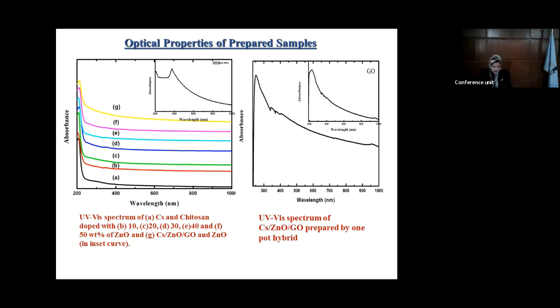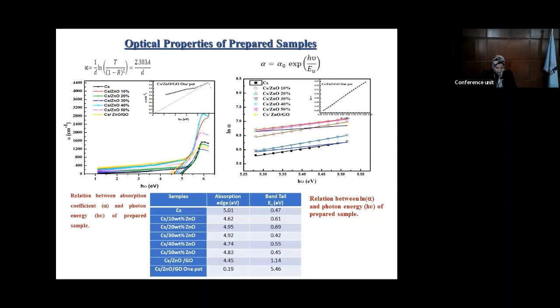The absorption coefficient is determined by the following relationship. The value of the absorption edge decreased compared with the pure chitosan, and the lowest value was for the one-pot composite. According to our correlation between ln alpha and hν, chitosan doped with both zinc oxide and graphene oxide gives a higher value of band tail energy compared to the other samples, which means that the one-pot composite has a higher degree of disorder and has high conductivity.